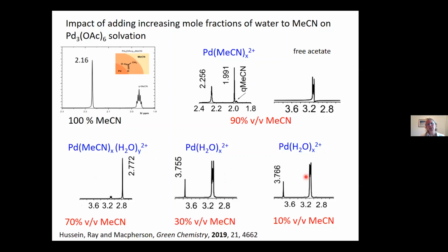And so what we did is we threw a lot of analytical techniques at trying to understand how the water and acetonitrile are bonding, but also what's going on with that palladium right in that inner solvation shell. Okay, what's that palladium bonding to? Because if you want to deposit palladium from the palladium 2+ salt, all those ligands have got to fall off. You've got to be able to have that process happen quite easily.